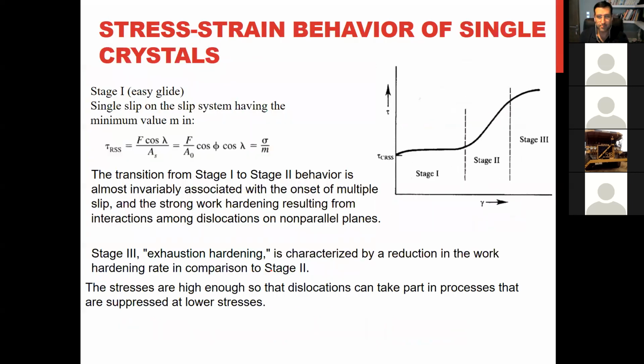So I think now we can understand easily this stress strain curve for, for example, a metal. Yeah, we can divide it in 3 stages: easy glide, strain hardening, and again the third stage that again deformation is easy. Yeah. So now you know this critical resolved shear stress that we calculate by this equation, and how this is related to the direction of the slip system and the tensile stress that you're applying, that already we talked about, that 45 degree. And if you have deformation in just one slip system, you have this easy glide part, yeah.